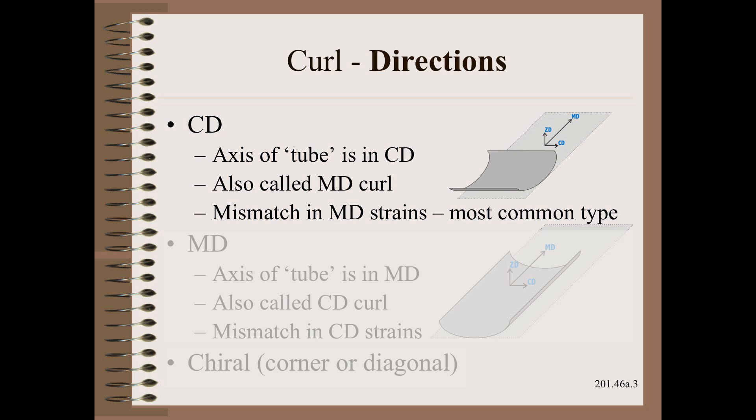The first point of confusion — and there are many with the subject of curl — is nomenclature for direction. The CD label we give here is what scientists and engineers would call it. Unfortunately, most plants call this MD curl. This means that clear pictograms are needed for any supplier or customer that has curled web. In any case, the mechanics are caused by residual MD stresses such that the top is shorter than the bottom, or vice versa.